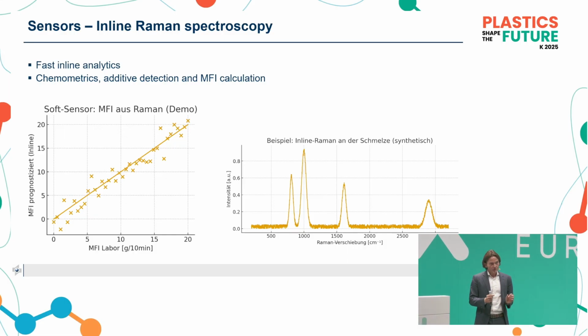What can you do? You can do chemometry, so you can analyze the composition of materials. And based on that one, you might also detect additives, and you can calculate inline a melt flow index. So that's something which is quite of value if you have it. And here you see just the experimental and the predicted data.